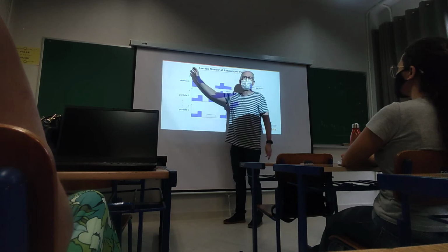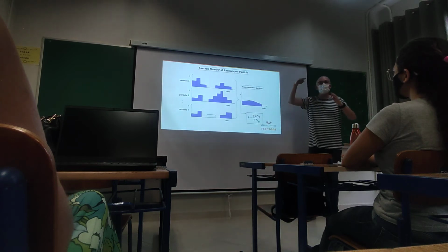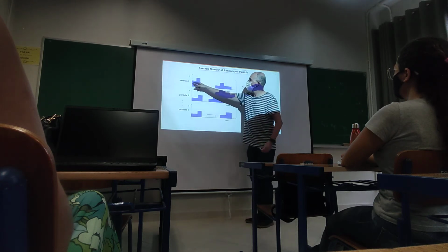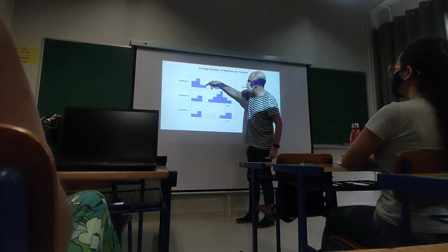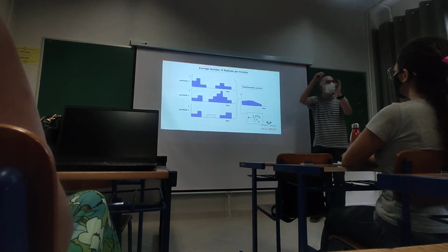In the polymerization we have 10 to the 17, 10 to the 18 particles. In each particle we have different mechanisms. So each particle has a different history of the number of radicals. In this one we have entry, the number increases, then we have termination, then we don't have anything, then we have again exit. So each particle will have a different number of radicals along the reaction.